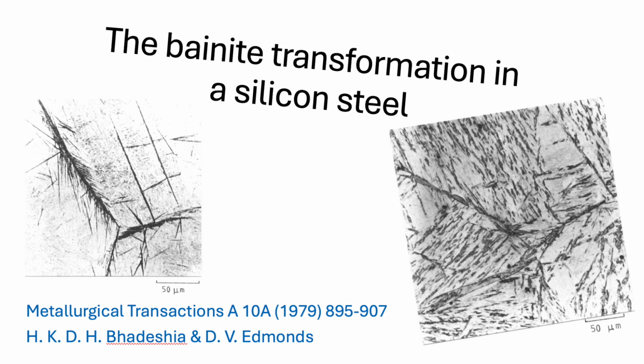What about defects inside the structure? Did they find anything there? Oh, absolutely. This was crucial. The bainitic ferrite itself had a really high density of dislocations. Which implies high internal stress. Something mechanically intense happened to form it, but the really telling part was in the retained austenite, the stuff left behind. What did they see there? They saw planar faults, like stacking errors, and actual visible slip steps right at the boundary between the austenite and the new ferrite. Slip steps, like the austenite crystal lattice literally slipped or sheared.